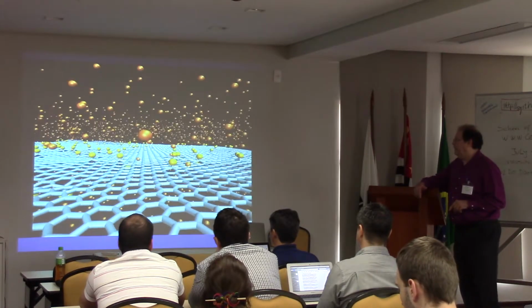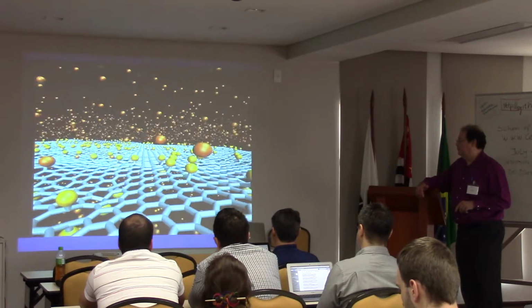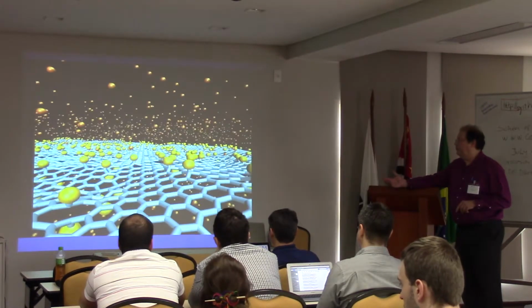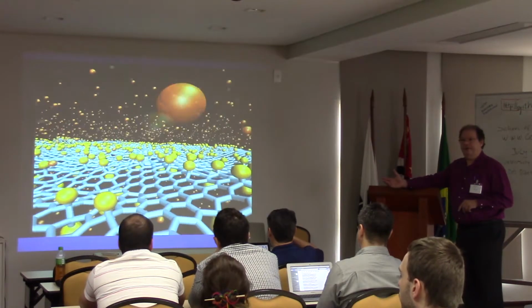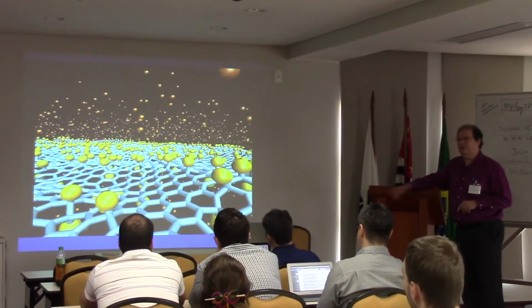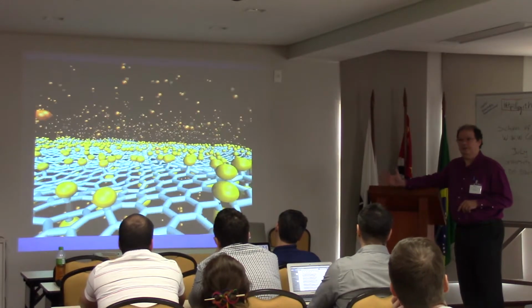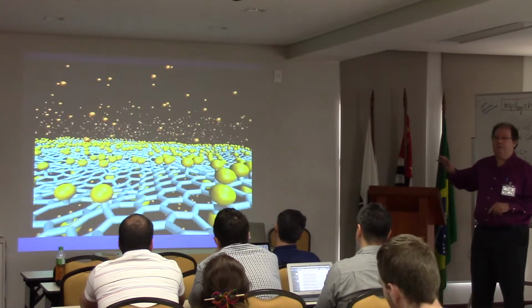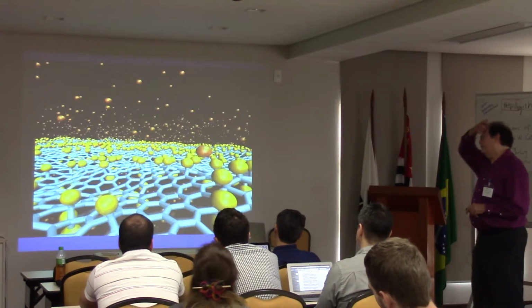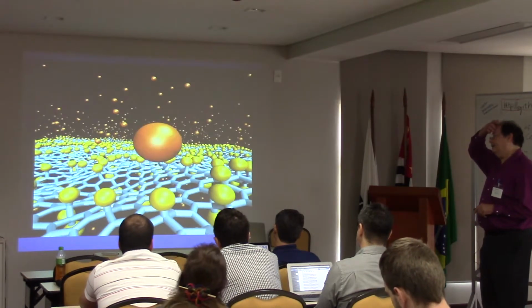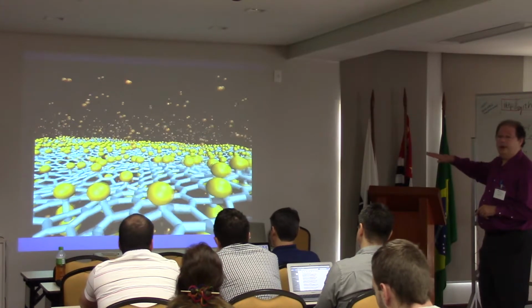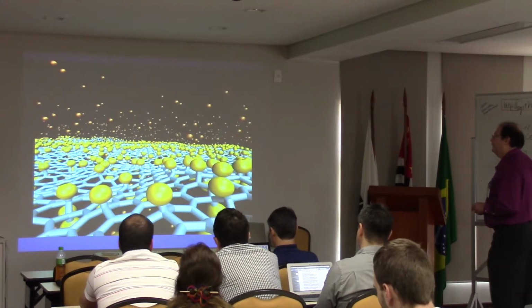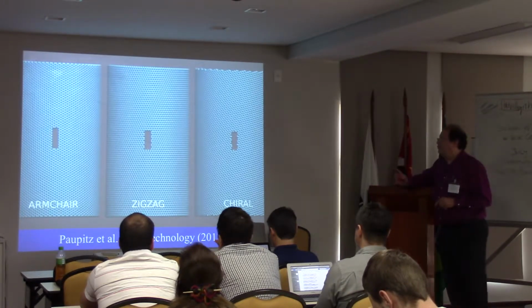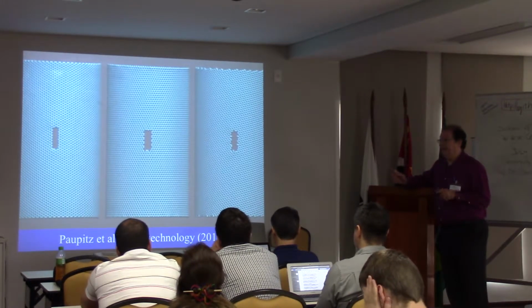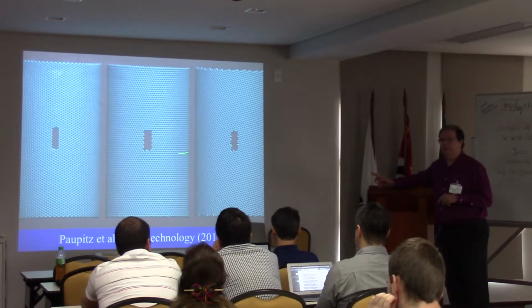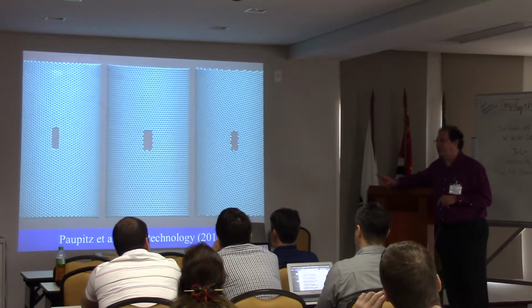See? They start reacting. The sp2 is being converted into sp3. If you continue with the simulation, you start creating defective areas. If you run this forever, you dissolve the material, exactly as in the experiment. So this is a virtual experiment of plasma etching of graphene that captures the chemistry much better. And there is no electron in the simulation. Okay. It's very good to study fracture, because in this time scale I cannot use a microscope to follow it. It's so fast, and I cannot have control of this.